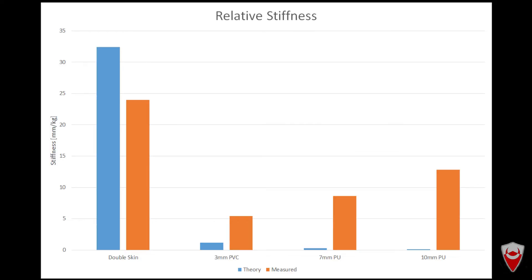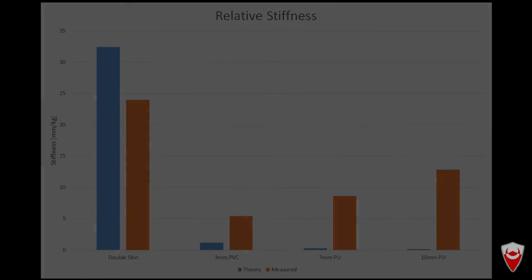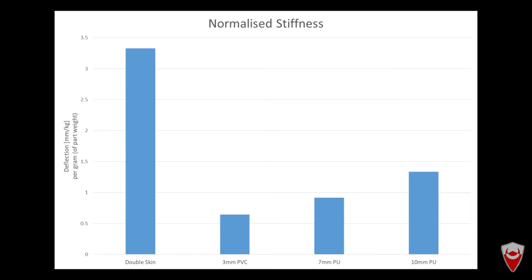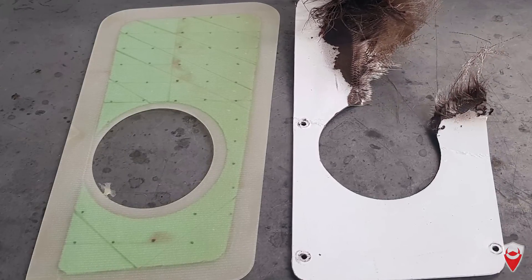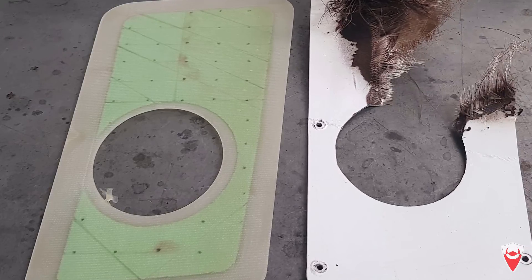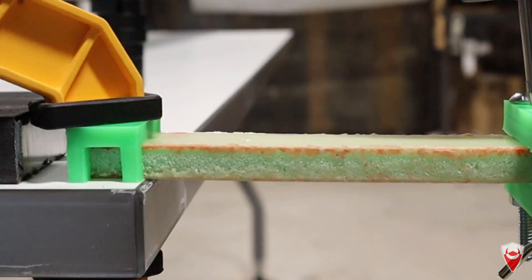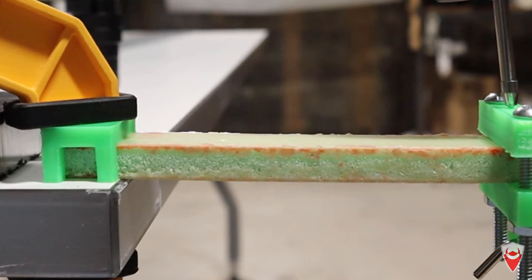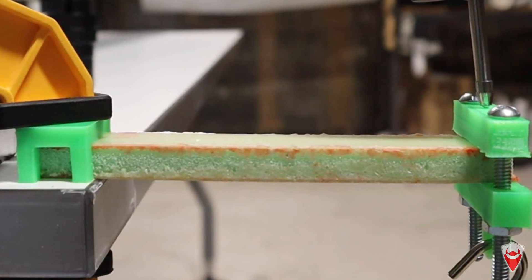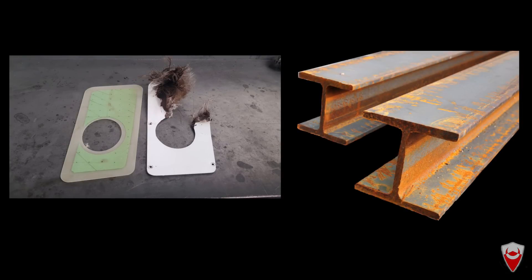The simple, obvious and wrong conclusion is that some thickness is good but more is worse. This experiment looks pretty dire for foam as a core material — however these results don't mean foam is useless. If we weight-normalise all these samples, all of the foam core parts are stiffer per unit of mass, meaning less deflection than plain fibreglass. So if you're trying to add stiffness to a panel, you're better off having a core than not. Thickness does help. The open ends are likely playing a large role, and changing both core materials and thickness simultaneously is confusing the issue. This has reinforced that composites are always more complicated to predict performance for than metals.